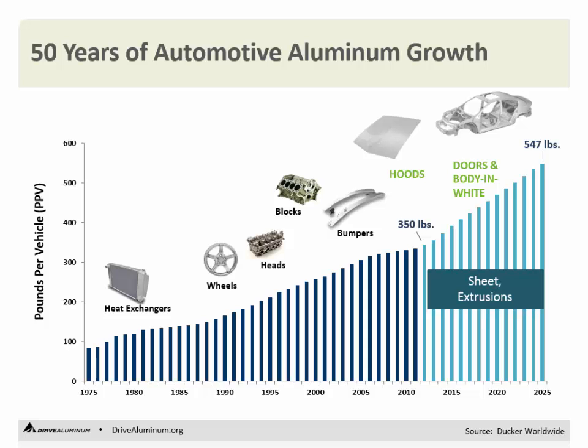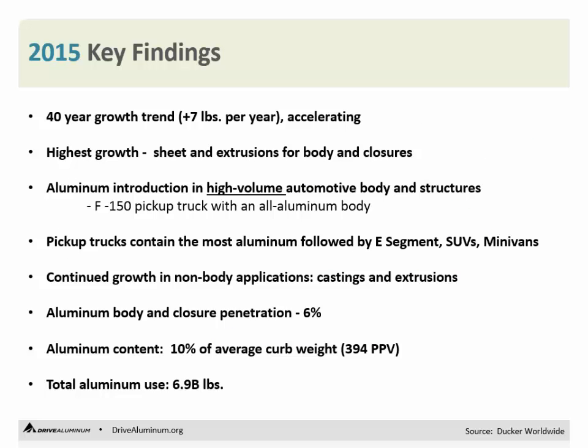Hoods started to emerge in the early 2000s, and hoods today are about 48% of the marketplace. And the growth going forward from today out to 2025 is predominantly in body enclosures: hoods, doors, trunks, body-in-white. The inflection point on this chart, about 2014, is where we've been growing at about 7 pounds a year increase in aluminum content since 1975. That inflection point at about 2014 starts to grow at about 14. It doubles to about 14 pounds per vehicle per year on average for the next 10 years. Most of that is in sheet and extruded product for body and closure panels. Basically, there's been 40 years of continuous growth, and we anticipate 10 years of even higher rate continuous growth.